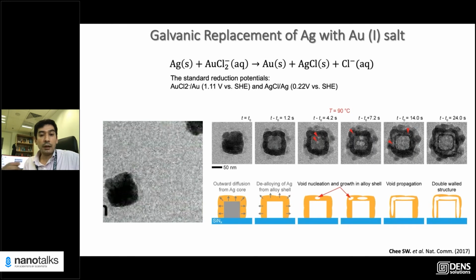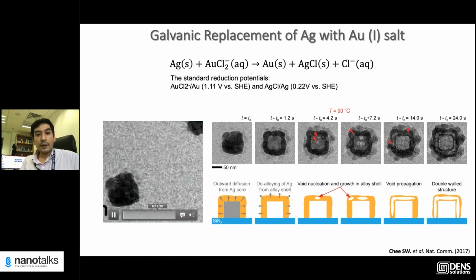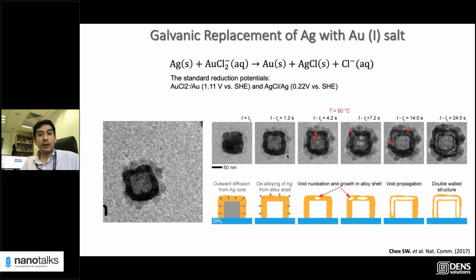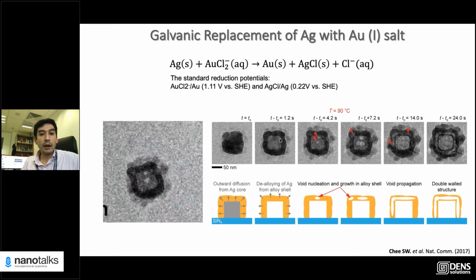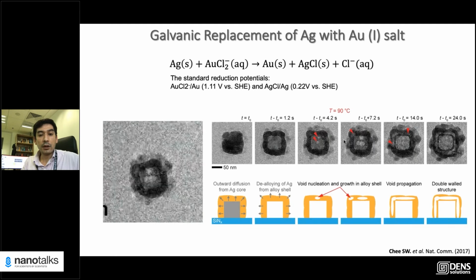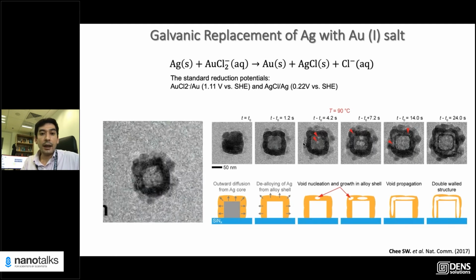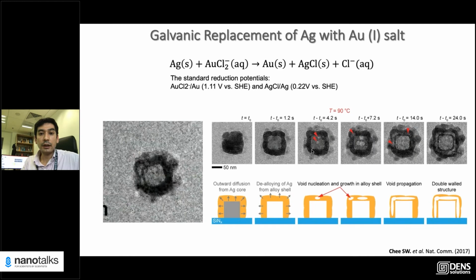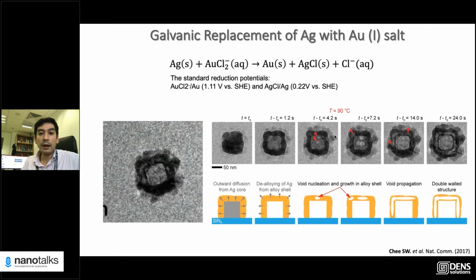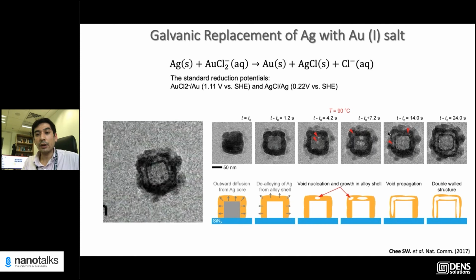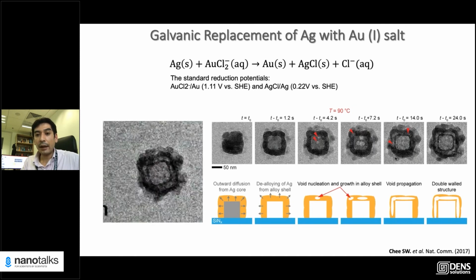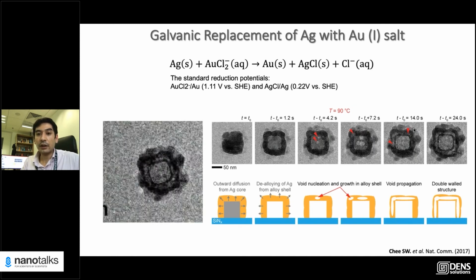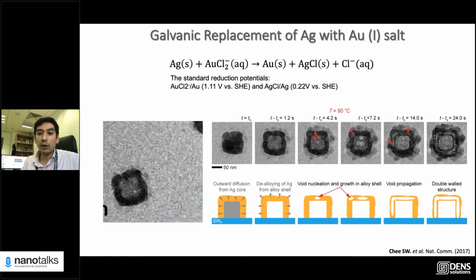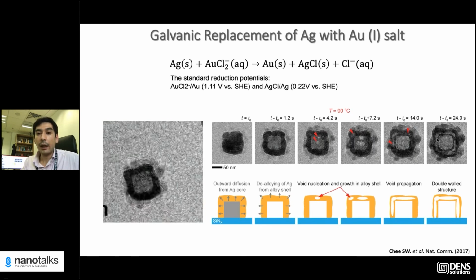If you're taking it away at a much, much slower rate, but you're continuously depositing the gold shell, then what's going to happen is your deposition is continuing, but you're taking it at a much slower rate. So you're etching inside, and then silver that's etched diffuses. So you form a silver-gold alloy, but new gold material comes depositing on the surface, and what ends up happening is you form a double-shelled nanostructure, because now this new gold on the surface is acting as a diffusion couple